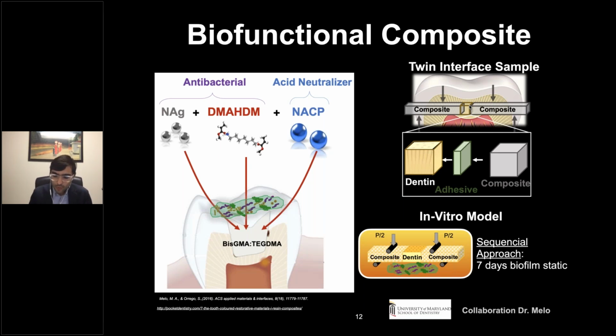The second thing we did was to create what we call a twin interface sample. This configuration is quite attractive because you really replicate all the bonding conditions you find in clinic. So what we did was cut a piece of dentin, a block 2 by 2 by 2.